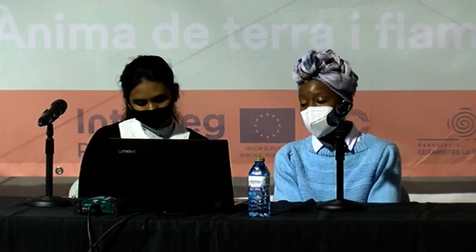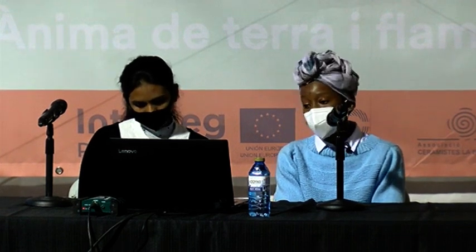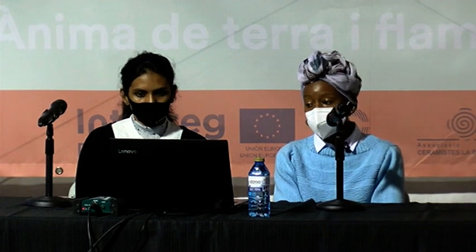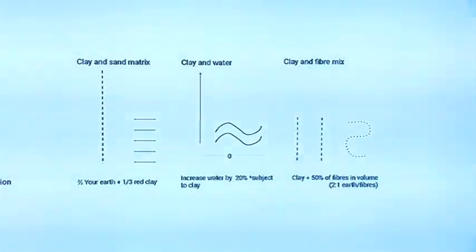In conclusion, with clay, we find that 2/3 of earth combined with 1/3 of clay is the perfect sort of combination to have. In terms of water, increasing by 20% normally gives us the best result, but this is subject to the clay because clay always reacts differently. The clay fiber mix, we know that having 50% of fibers is more or less the best composition to have a well-extruded material.